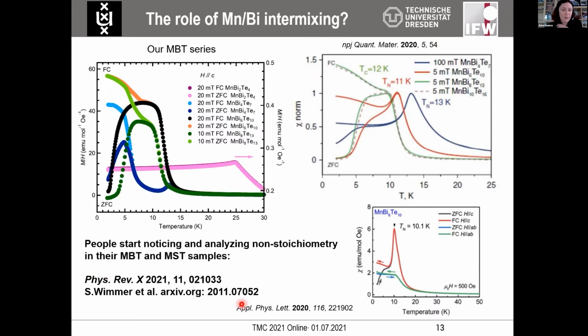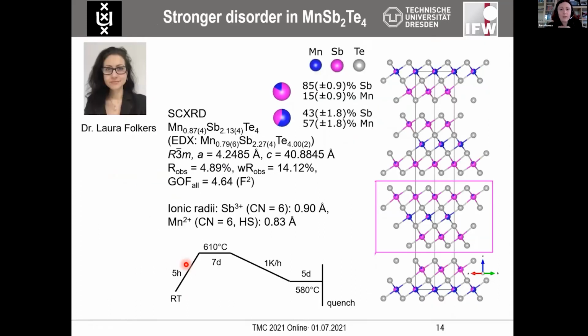So there are two very nice papers here from the different groups reporting on what can happen in the MST analog. So let me go there and start by presenting the data that we got in our group. So we tried to grow these analogs by slow cooling of the melts. We quickly saw, just like other groups, that this compound does not have a narrow range of stability. It exists in quite a large interval, so it can be obtained in different temperatures. But then when you get your crystal or your powder at a certain temperature, it may have slightly different composition and therefore different magnetic properties.